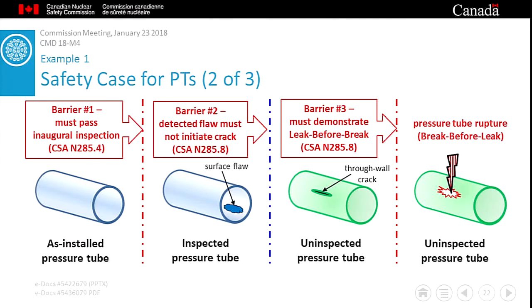If CNSC staff accepts that assessment, barrier 2 has been crossed. The licensee can operate the affected tube out to a specified deadline, at which point they must re-inspect the flaw to ensure that DHC has not initiated.